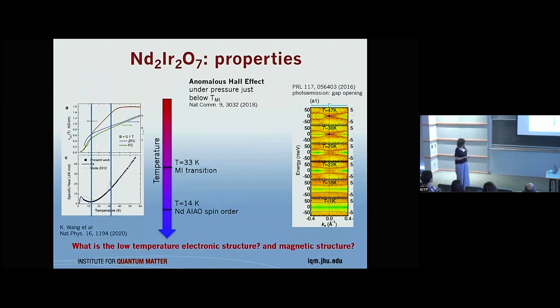Okay, so what do we know about this material? We know that it actually has two transitions. One is at 33 K, which is the iridium ordering, and it can be pretty sharp in specific heat. And there is also neodymium ordering, which is observed below 14 K, and it's a very broad crossover. By the time we started, there was an understanding that neodymium moments order in the field of the iridium moments, which are ordered all-in, all-out. That the electronic structure is changed by the magnetic ordering was already seen in the conductivity data published in the work with Dick Vanderwaal and Peter Armitage.